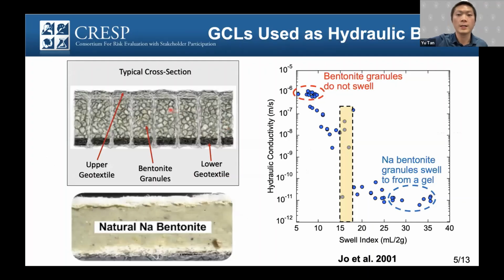Before we go to our test, let's take a close look at GCL. So what is GCL? This is the typical cross-section of GCL, a geosynthetic clay liner. It usually contains granular bentonite, this part, sandwiched by two layers of geotextile. This granular bentonite is usually sodium bentonite. When it's hydrated with dilute solution, it will form this gel structure at the bottom. You can see that it's pretty impermeable.